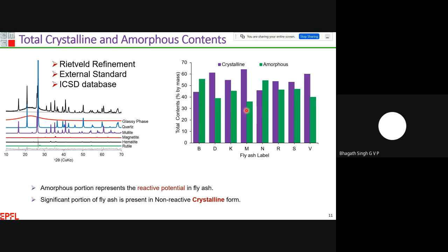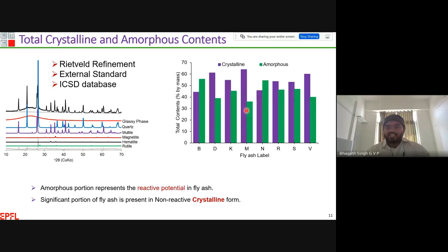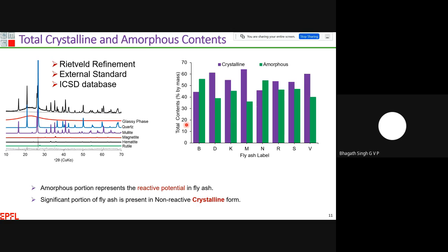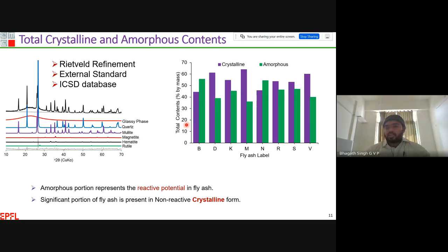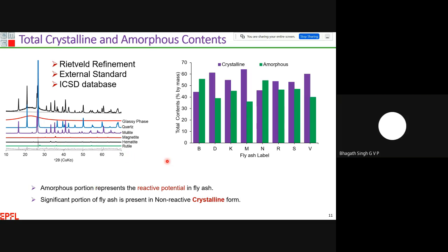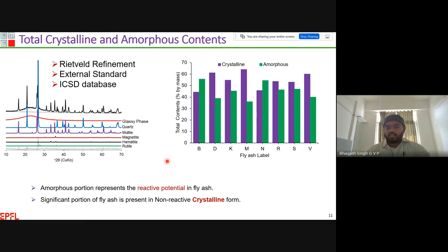This indicates that the reactive potential, the reactive components of fly ash, will vary from one source to another. And overall, in all these fly ashes, a significant portion is present in the non-reactive crystalline form. The crystalline form will not react in the system; it will simply sit in the system. But the amorphous portion is responsible for the reactive potential of fly ash.